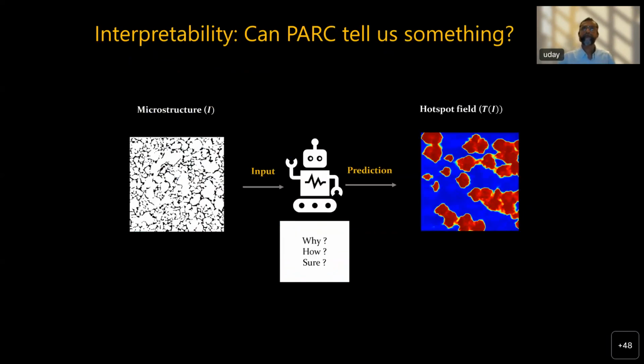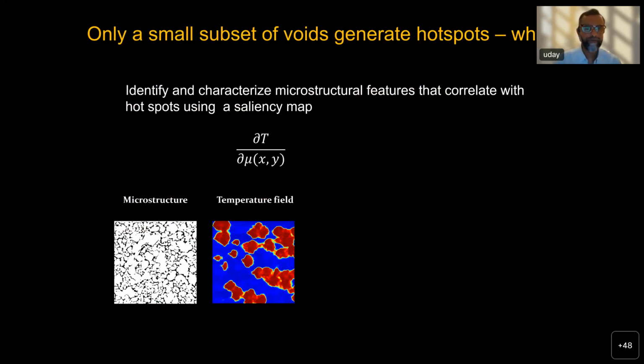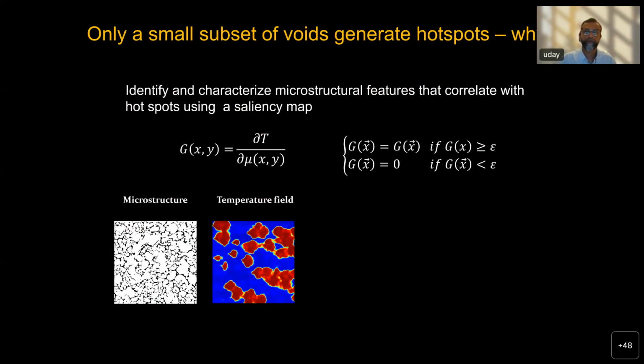So aside from this, we also asked the question, can PARC tell us some information about the physics? From our simulations, we noted that only a small subset of voids generate hotspots. And why is that? What is particularly interesting about those critical voids? And can we get information about this? So we used the saliency map, which is a derivative of the temperature with respect to the microstructure. And we have these two fields, the temperature field and the microstructure field. So we can then establish the sensitivity matrix. And that is what I'm calling the saliency map field.